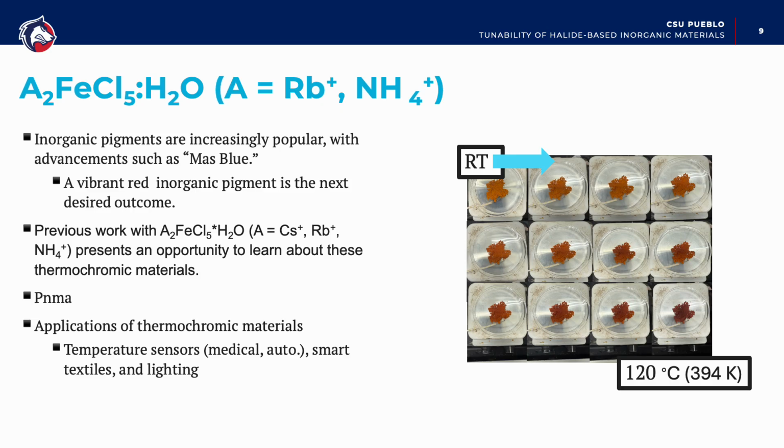It has a similar space group to the indium analog, but the properties of the material are very different, as evidenced by the fact that it is orange and thermochromic under white light, whereas the indium analog is strictly a white powder. The synthesis of such a material was the exact same, however, which was interesting: changing one atom gave us a totally different material with totally different properties.